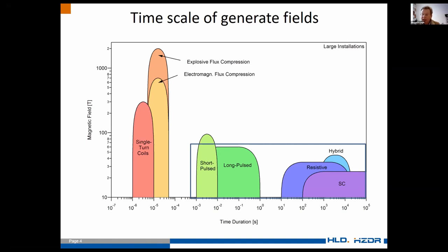But if we talk about higher fields, of course, we should use pulsed field magnets. We can distinguish between short pulses and long pulses. The difference, of course, is energy. If you put more energy in the magnet, you need more time for cooling everything down. For instance, with long pulses, with a pulse duration of about 1 to 2 seconds, this is quasi-continuous; you pulse and you wait 24 hours until the next time. For short pulse magnets, for instance up to 60 Tesla, we can pulse each hour, or a couple of hours, depending on the pulse duration.